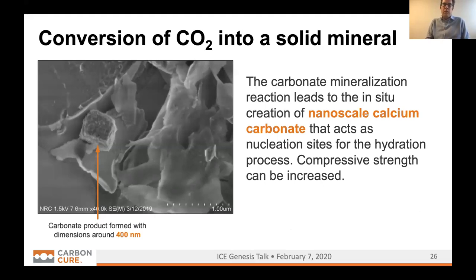We've done some looking around at the lab scale for evidence of this material, and we can find that upon injecting CO2 into a paste, you can see carbonate minerals, and they'll have a dimension of around 200 to 500 nanometers, it would seem. And so by taking this injection of CO2, you've now mineralized the CO2 in the concrete as calcium carbonate, and you've generated an in situ nanoscale calcium carbonate particle. And this particle acts as a nucleation site, and the downstream hydration processes that do occur will be impacted by this nanoscale addition. What we are seeing is concrete producers doing this can make stronger concrete.